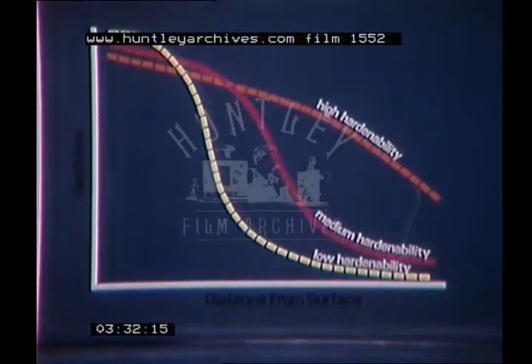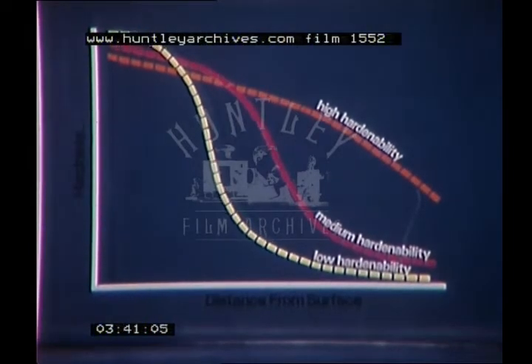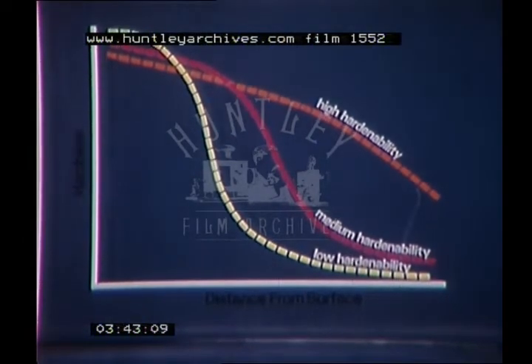The depth of hardness curve varies with the analysis of the steel, particularly the carbon content, and also the temperature from which the roll is hardened. As the depth of hardness increases, the hardness at mid-radius, where the hardening stresses are most critical, will also tend to increase, and this puts a practical limit to the depth of hardness.